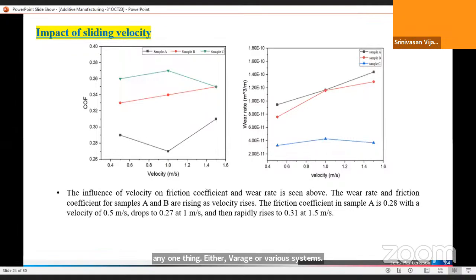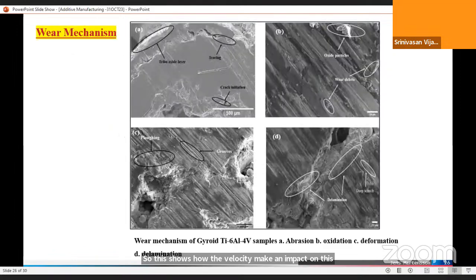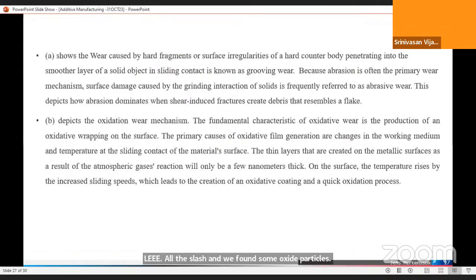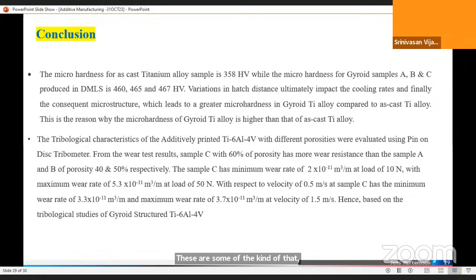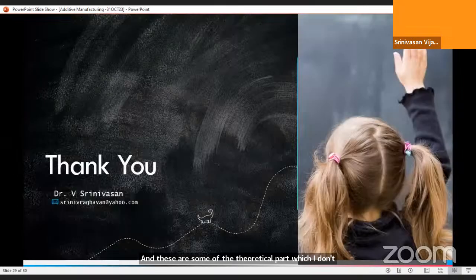This shows how the velocity makes an impact on the coefficient of friction and the wear rate. And these are some of the SEM pictures. What kind of mechanism we obtained for these oxide layers, how the crack is initiated. Here the ploughing type of mechanism. Here the grooving. Here the material has been delaminated out of the scratch, and we found some oxide particles. These are some of the wear mechanisms we obtained, and the theoretical part I don't want to go into because we have already lapsed more time on this.